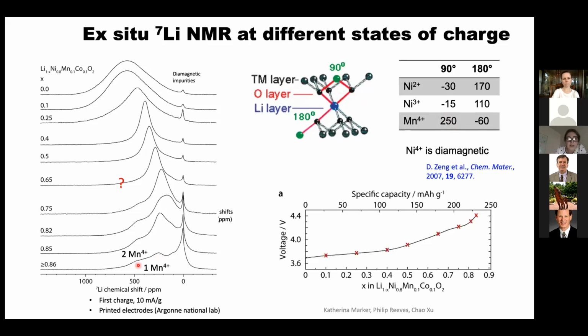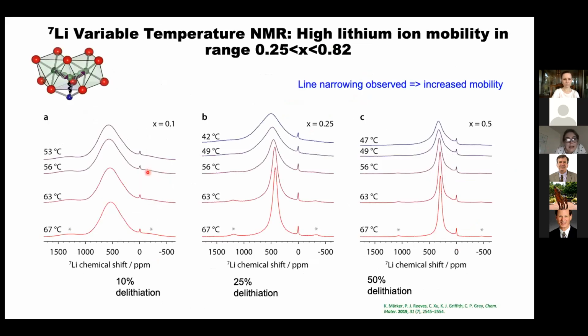So that's nice, but we haven't explained this. And what's going on here is that this is the signature of lithium mobility. And you can probe that by doing variable temperature NMR. So as you go up in temperature, the lithium ions move more. And so in this case, if you get sharpening, that's a clear signature of mobility. And so in this regime at 0.5, the lithium's already moving quite fast, even at close to room temperature.